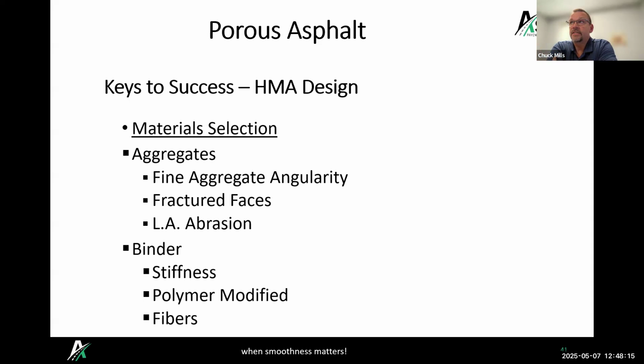I know some people have done some research when we were doing the roads and the road designs and how much traffic it could hold up to. We really were able to design a slightly lower air void mix that could hold up to higher traffic. The City of Ann Arbor, when they were designing their roads, actually did a super paved mix design on it at a lower air void, and compacted it and actually measured density.